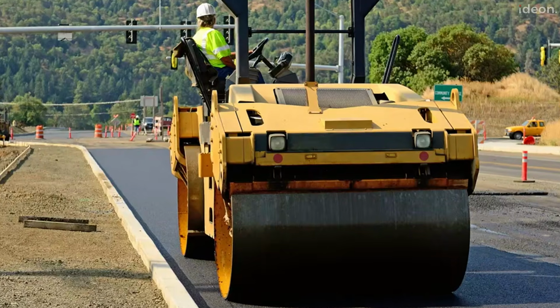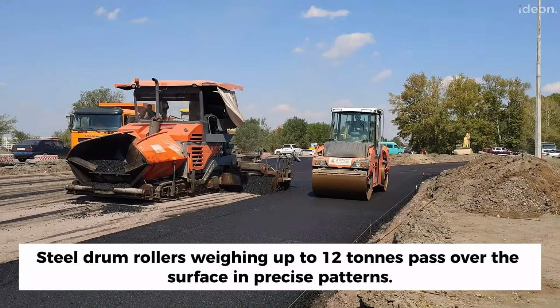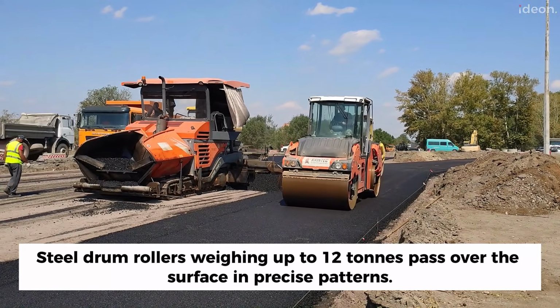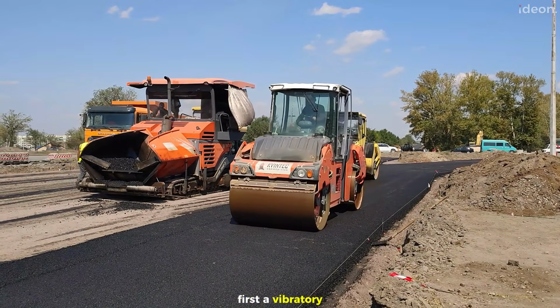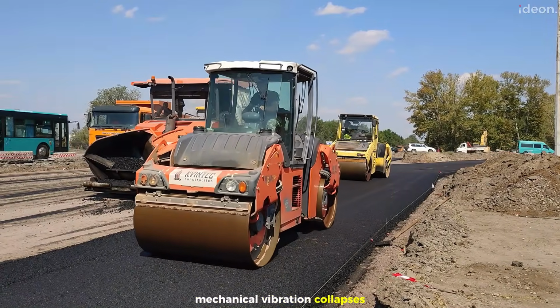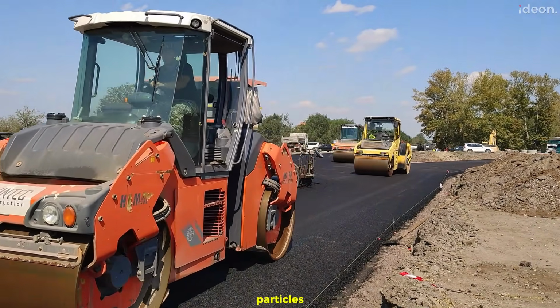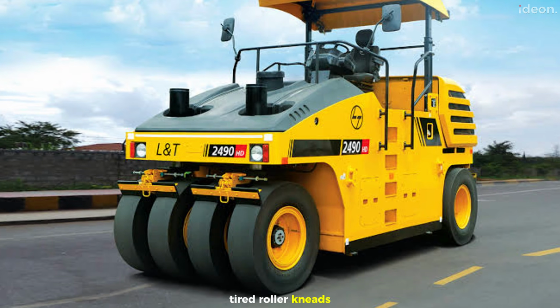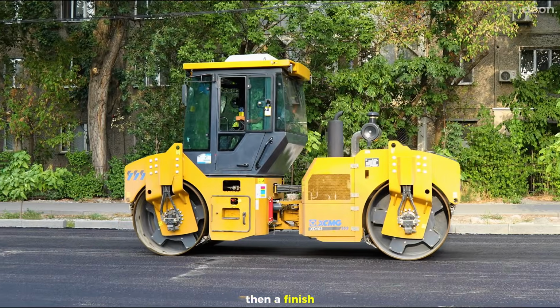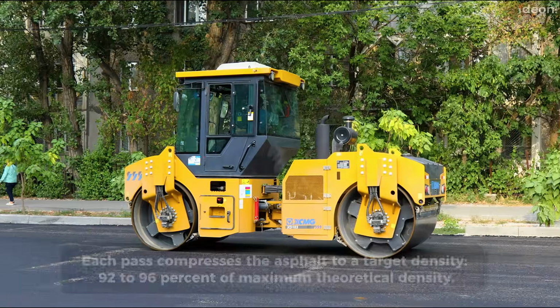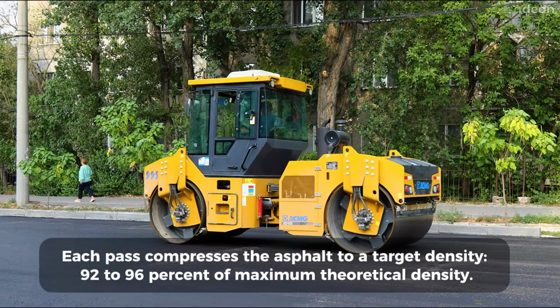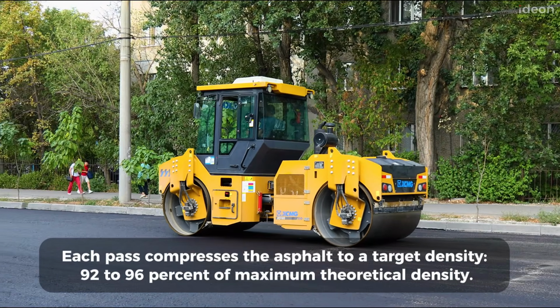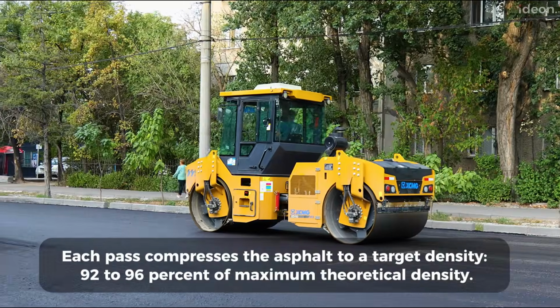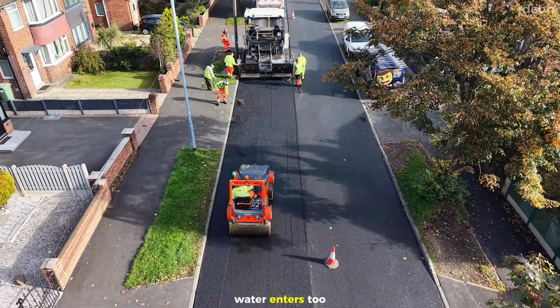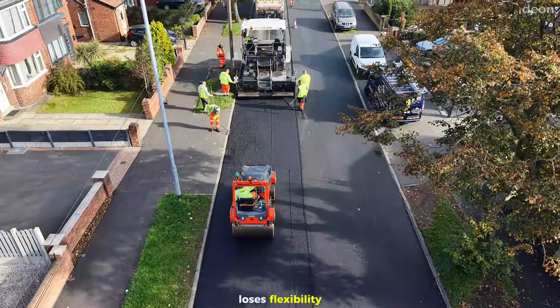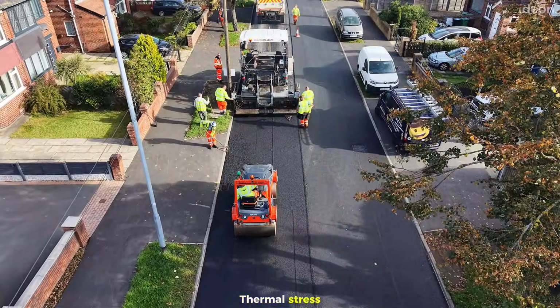Then the rollers arrive. Steel drum rollers weighing up to 12 tons pass over the surface in precise patterns. First, a vibratory roller. Mechanical vibration collapses air voids between stone particles. Then, a rubber-tired roller kneads the surface and fills gaps. Then a finish roller for the final surface. Each pass compresses the asphalt to a target density, 92 to 96% of maximum theoretical density. Too low and water enters. Too high and the road loses flexibility and cracks under thermal stress.